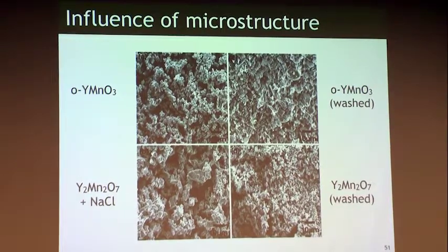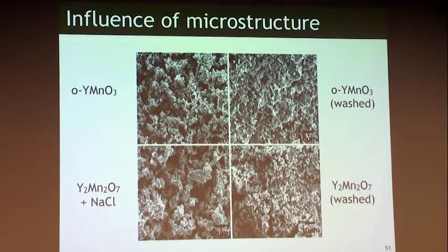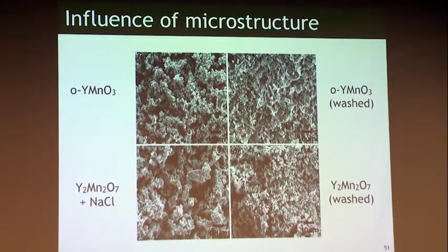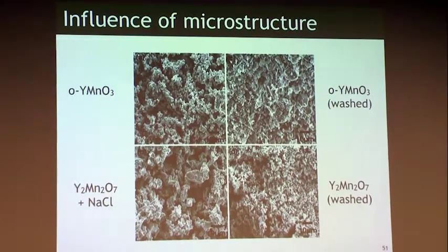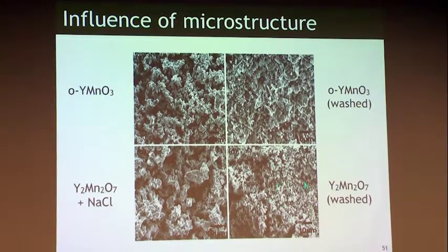Whether or not that's the actual grain size, we haven't looked, but they're getting reasonably largish for relatively low temperatures. Granted, this was at probably the 850 degrees Celsius reaction. The pyrochlore has these tiny little particles that are definitely less than a micron, but very sharp Bragg peaks. So there's absolutely some size dependence.